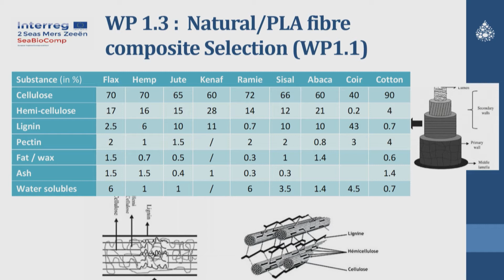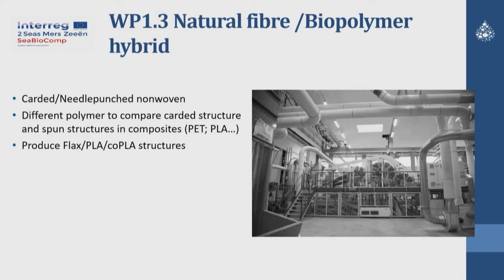So if we look at properties, you will see clearly that the fibers which have the most cellulose or more hemicellulose are the stronger fibers, so flax, hemp, and at the second level, jute or kenaf. So that's why we chose flax, of course, as the natural fiber for hybrid textile used for composite. So we use carded needle-punch non-woven. You have the card in a picture, so you can understand better.